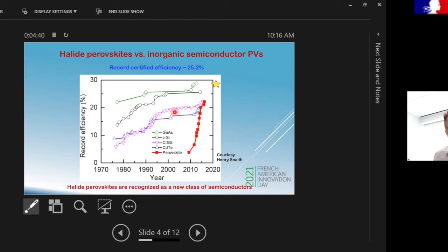And this has driven a lot of interest in this material system, to understand its properties and to engineer applications based on it. Now, the star that I show is actually close to 30%. This refers to a silicon-perovskite tandem device that was recently published by a group in Germany, where they've shown that you can get near 30% efficiencies if you combine silicon and perovskite. And so that's probably the first thing that would come to market as people begin to think about commercializing these devices for photovoltaics.